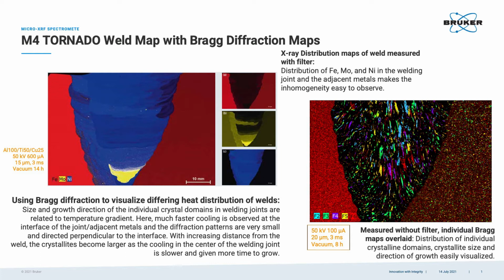Do you think that they find differences based on grain size on the composition? I would think that would affect it a little bit, if they're looking only for composition, but yet they have a huge variation in grain size. Yeah, so if you look at their maps, they have the Bragg diffraction superimposed on their segment on there. So they can account for that. But it doesn't really affect quantification so much. On the visuals, it just doesn't look so good. I suppose if you were looking for really, really precise and accurate numbers, that might be more of an issue. Yeah. But since they're not, no worries there. That was a good summation.